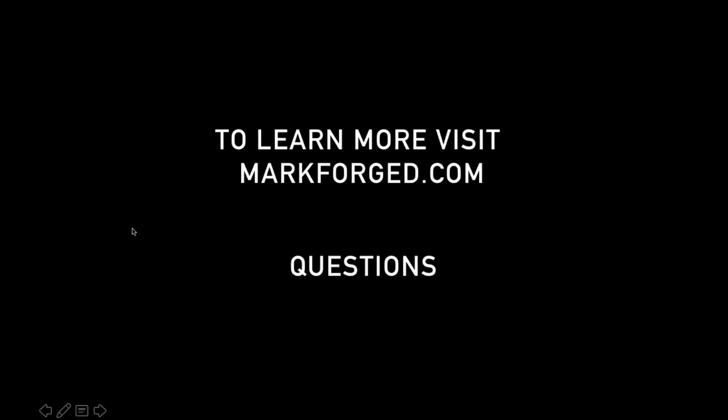What is the Z direction strength? In Onyx, Z direction is the strength of plastic, and specifically, it's about 80% of the published strength data for Onyx. But again, you can very easily design around any Z strength requirement you need. There's a lot of different application examples of how to do those designs to take Z strength into account. So we find that it's very rarely a limitation, even without taking special design consideration. Just orient your part in the correct direction.